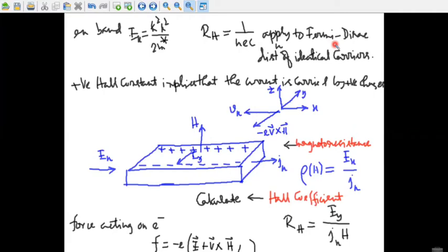We can furthermore see that on band theory, vacant states near the top of an otherwise filled energy band behave as if endowed with a positive charge. States of this character give rise to the positive Hall constants. The anomalously large value of the constant for bismuth is interpreted on band theory as given by a low concentration of electrons outside nearly filled bands.